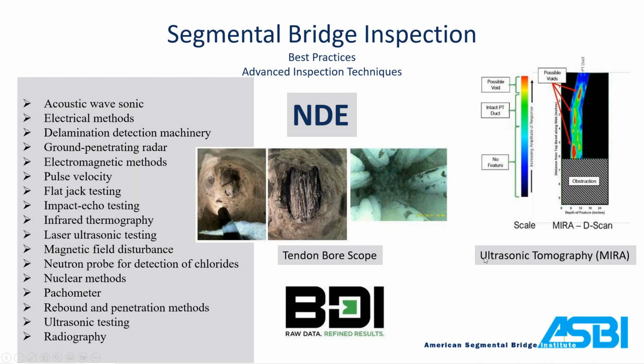You can do this ultrasonic tomography, these MIRA scans that actually give you an idea of where some grout voids may be or what the condition of your tendons are. And then you can actually do a small core hole, get a bore scope in there, and actually get a visual on your steel and see what kind of condition it's in. So that technology does exist to look at these things in further depth.